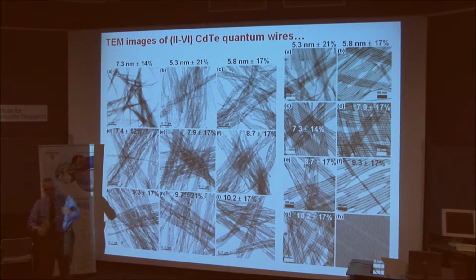So when you come back from lunch, you'll see a little clear solution at the top of your vial. If you wait long enough, they'll all settle out into these sorts of bundles. But you can merely swirl the vial and they'll go right back up into suspension again. And that's because they have long alkyl chain surfactants attached to the surface, which give them dispersibility.